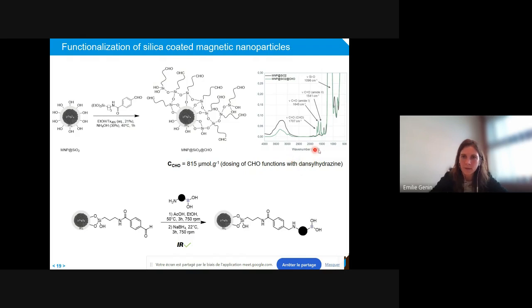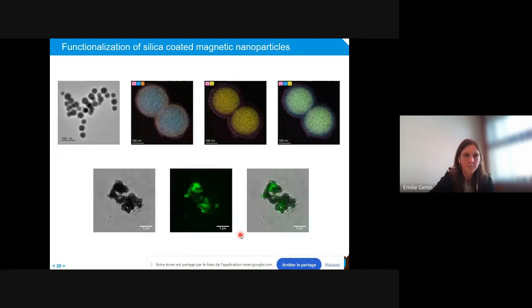Once again, we use infrared spectroscopy to compare the two spectra, that of the pristine nanoparticles and that of the hybrid. As you can see, we have the characteristic bands proving the functionalization. After we did the post-functionalization by reductive amination, infrared confirms that we got the targeted system.